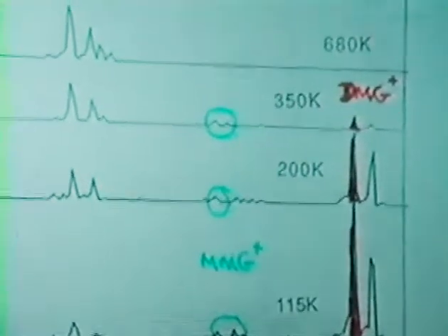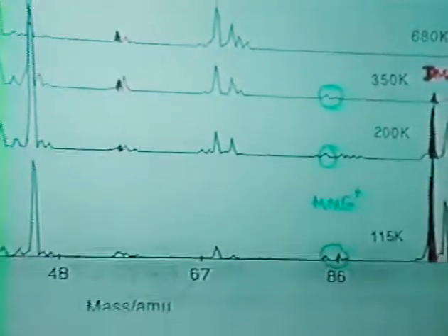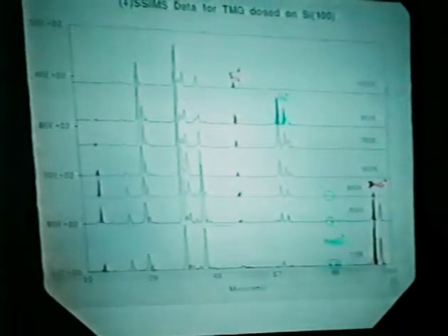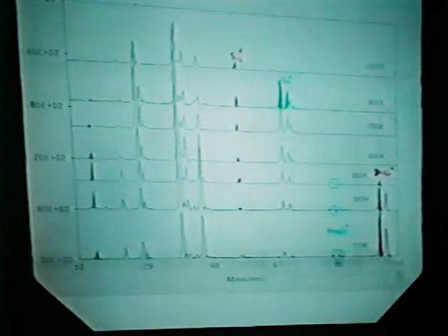So let's just look at the bottom one first, and then compare that to the top one, and look at the right-hand side. Over on the right-hand side, there's a dimethyl gallium plus signal. Look at what happens. I've colored that red: 115 strong, 200 Kelvin strong, 350 Kelvin much weaker, 680 Kelvin nothing. So somewhere in that temperature range, that particular species disappeared. There's another peak around the 80s in circles in green. It's much weaker, monomethyl gallium plus. Look at the gallium signal, just above 67. Starts weak, gets strong, and then disappears after 680 Kelvin.